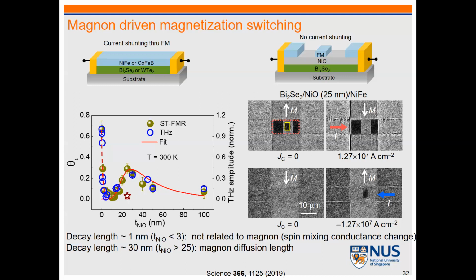And once we flow the charge current from the left electrode, you can switch from black to white and white to black depending on the charge current direction. So we can really show that indeed we can use this magnon current to switch this magnetic isolated element.